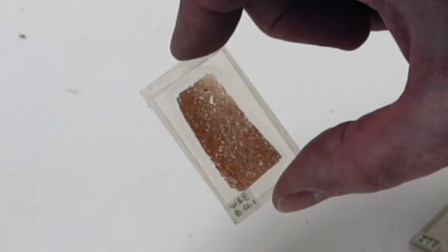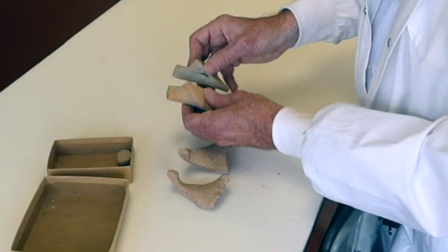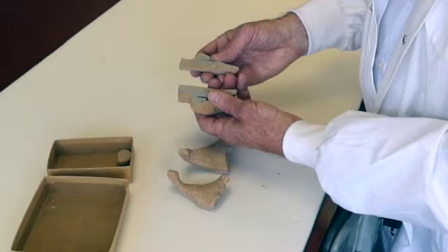In some cases, we actually saw the sherds vertically to create a cross-section, especially if we plan to use thin sections for petrographic analysis. Once the thin slice is removed in order to make the thin section, we can still make use of these leftover halves of the sherd to make some macro observations on it, as well as to make it easier for us to draw the pottery.